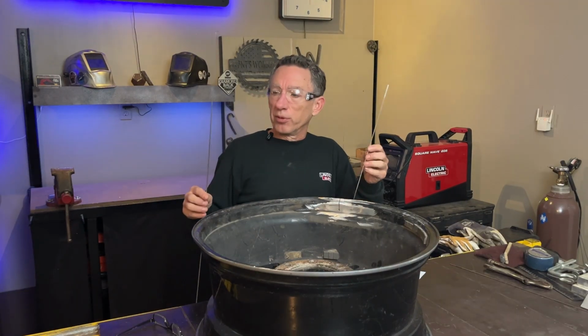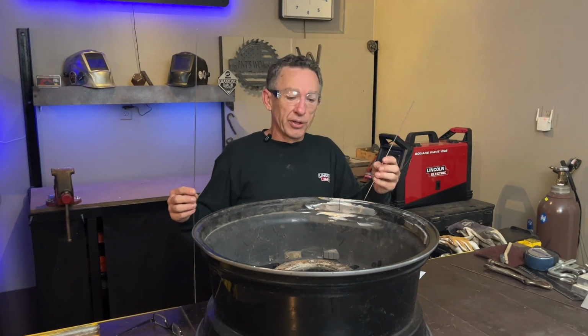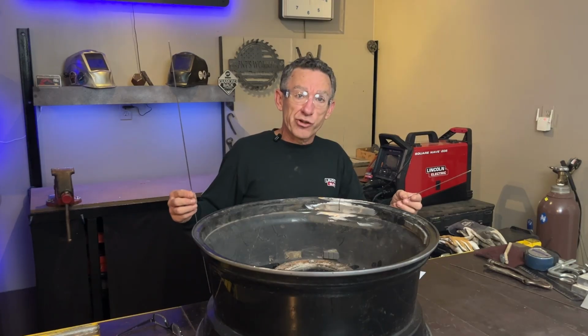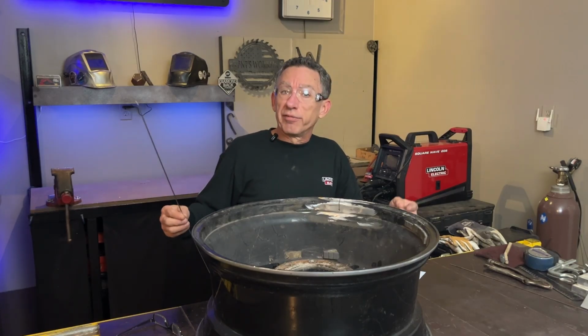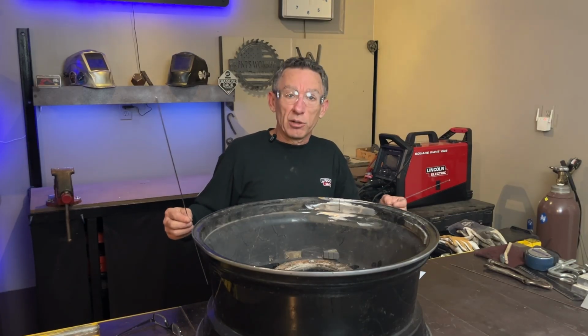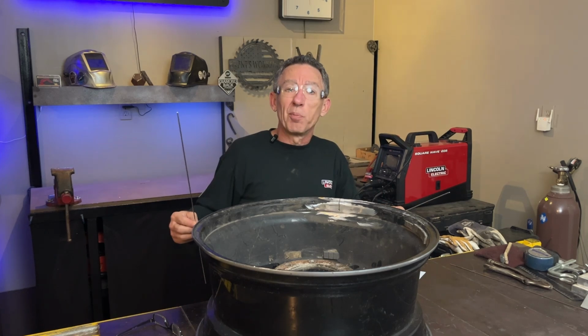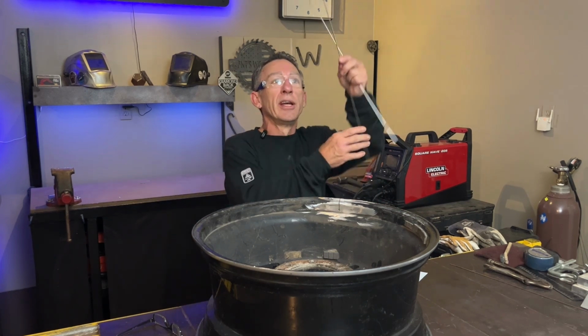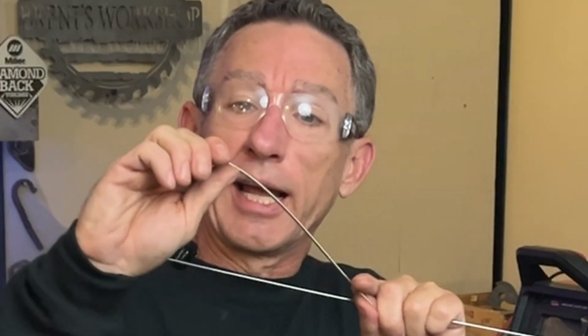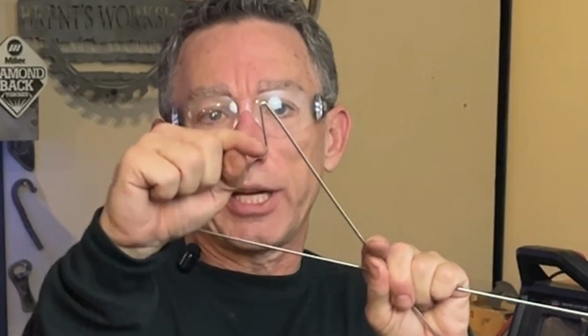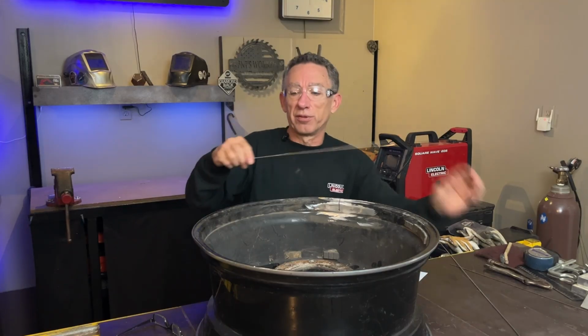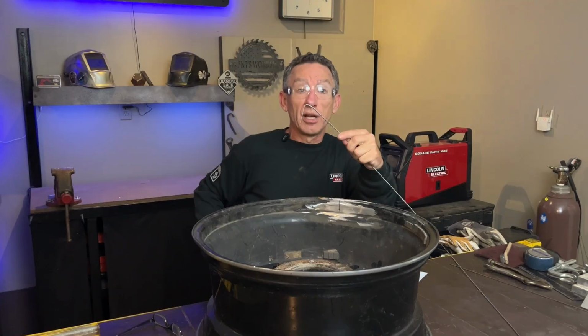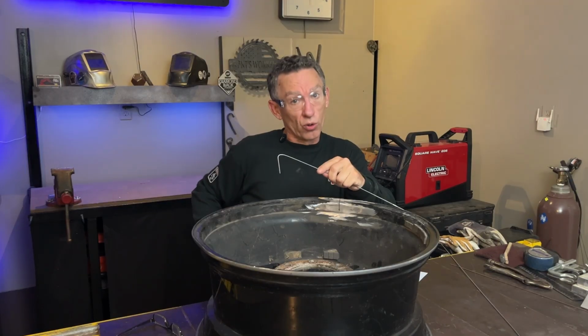So here's a tip if you're looking at aluminum and you don't know what alloy it is. I typically have two alloys in my shop, 4043 and 5356, and I can tell them apart easily just by doing a simple bend test. Watch this. If I take this 4043 and I bend it, it kinks right where I bent it. You see that sharp kink? Now, if I take this piece of filler rod and I bend it, it wants to curve around my thumb. That's 5356. And that's a good way to tell what filler you're holding in your hand.